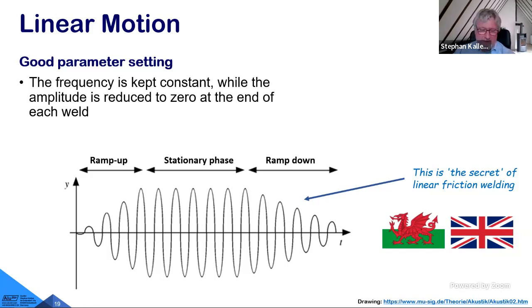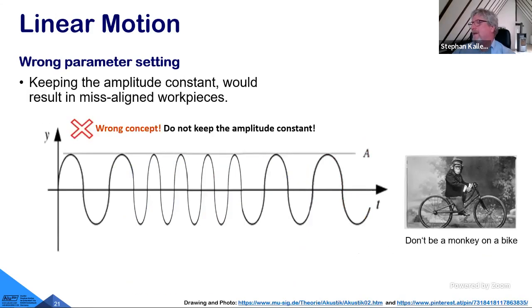But the most important thing that you learn today is the secret of linear friction welding has been divulged today. The secret is that you do not reduce the frequency at the end of the weld, but you ramp down the amplitude. So the movement gets from plus and minus 5 millimeter, plus and minus 4, plus and minus 3, plus and minus 2, plus and minus 1 to plus and minus 0. That is the way how you can align the components so well against each other. That is difficult. You need a special gearbox to do that. It's not like the monkey on the bike. The monkey on the bike, at the end of his trip, he is with the pedal somewhere in the space, and that's the wrong approach.